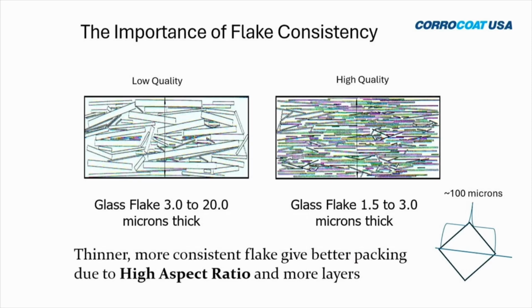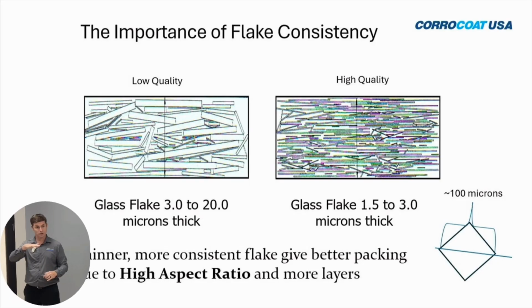In the early 80s, however, we became dissatisfied. We wanted to continue to get better. We're always looking to improve. So we started an R&D project. The owner said, yeah, I think I can do this better. So he developed a method that makes glass flakes utilizing molten glass that is poured down onto a spinning table. You vary the size and the thickness and the consistency of those glass flakes by varying the speed, the centripetal force. Now you can get glass flakes that are 1.5 to 3 microns thick. That's what we use for protective coatings.